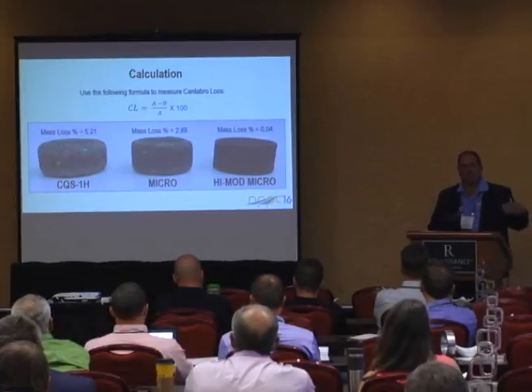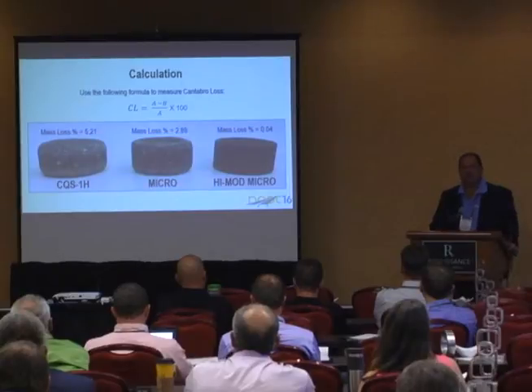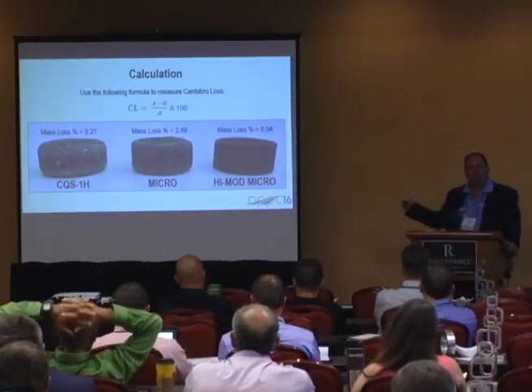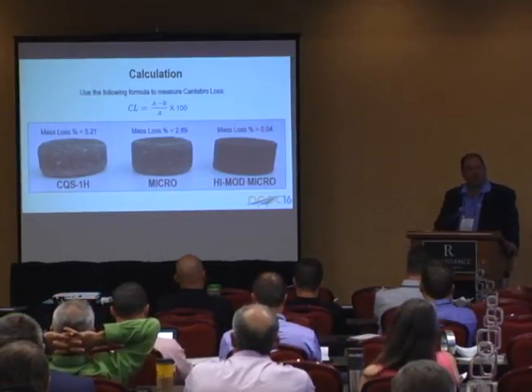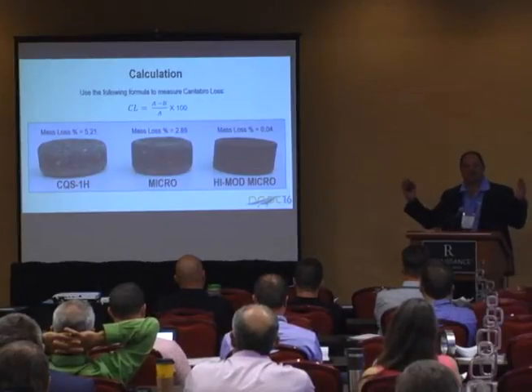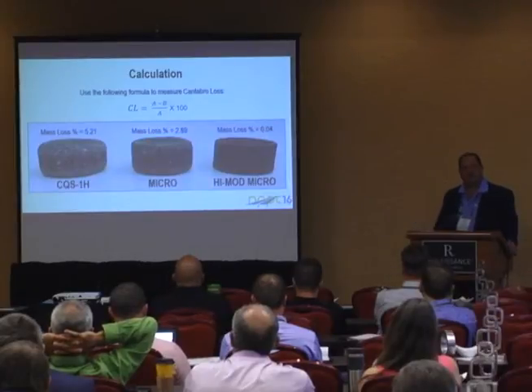Now, if you think about the improvement, we go back to that first picture up in Tahoe, and we saw that CQS slurry with some abrasion. It was time for a micro on top of that. We saw the micro performing, but with the high mod, we're not seeing the damage there. This is the expectation of maybe 3 to 4 years longer life, going back to NCAT, where we saw that extension in traffic before we saw fatigue cracking or cracking developed. This is what we expect to see with this.